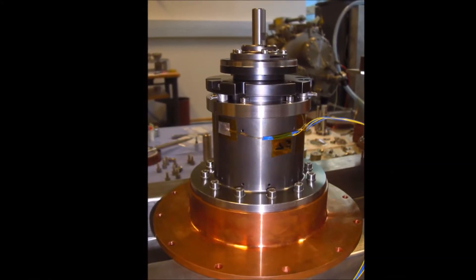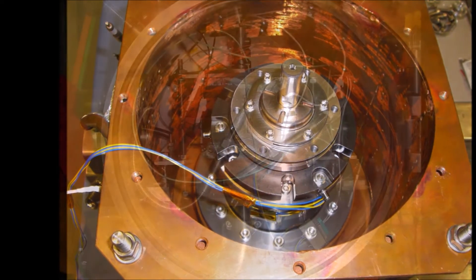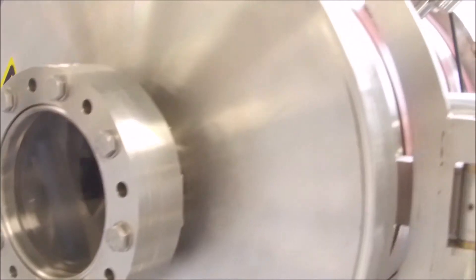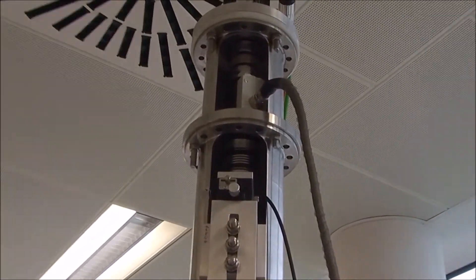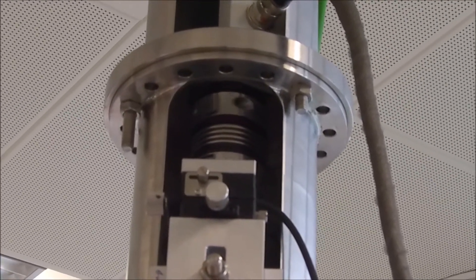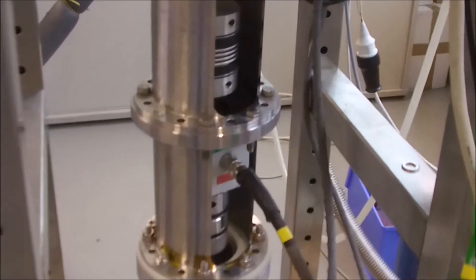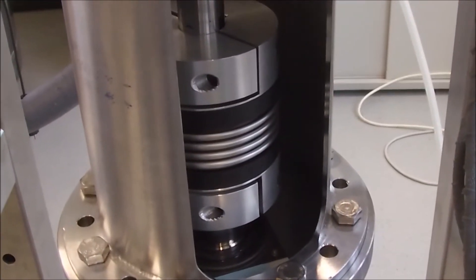The solid lubricated gears were assembled into test boxes. This test box was inserted into a newly developed vacuum test device. In this device, gears were tested under thermal vacuum simulating their working conditions in space. Several gears with different coatings and gear designs were tested for durations up to several weeks. Towards the end of the project, lifetimes were found which fulfilled the requirements by the space customers.